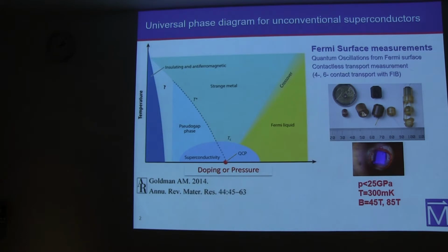What we look at with those compounds is actually the Fermi surface of those compounds and how the Fermi surface evolves with either doping or pressure, in our case pressure. We measure the Fermi surface by looking at quantum oscillations, and for that we do contactless transport. And we use pressure cells. This is a picture of our pressure cells. The phase space that we work in is pressures up to 25 GPa, helium-3 temperatures, and static fields up to 45 Tesla, or pulsed magnetic fields up to 85 Tesla.